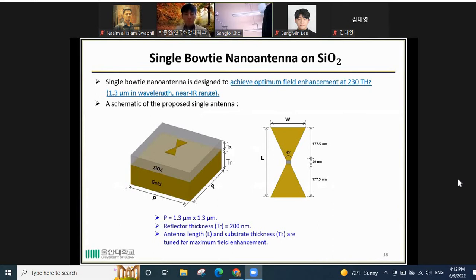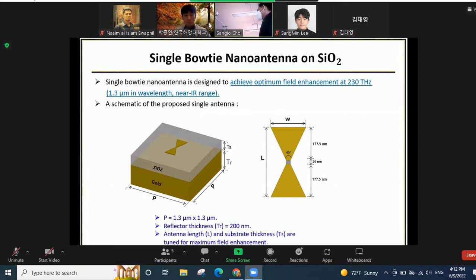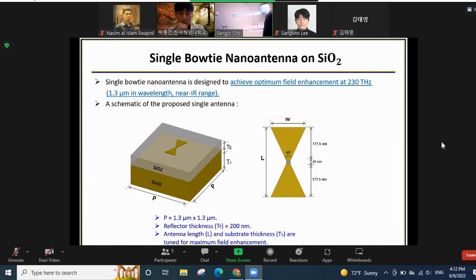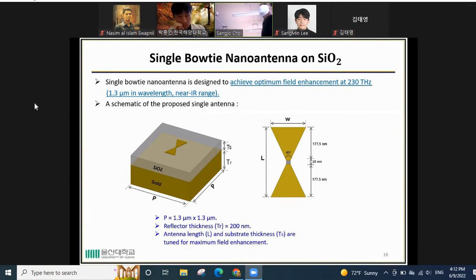So we start our design with the single bowtie nanoantenna on a silicon dioxide substrate. The aim of this design is to achieve optimum field enhancement at 230 terahertz, or 1.3 micrometer in wavelength, which is in the near infrared range. This is the schematic of the proposed single antenna design. We use a unit cell size of 1 lambda, 1.3 by 1.3 micrometer, and the reflector thickness is set to be 200 nanometer. And also we tune the antenna length and substrate thickness for the maximum field enhancement at 230 terahertz.